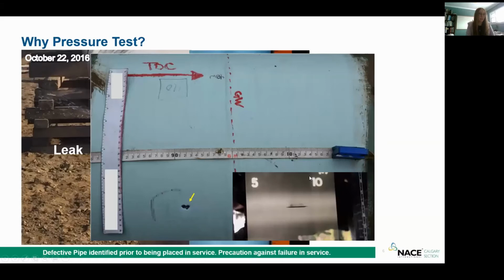Next here is a below ground mainline test, which was unable to hold constant pressure. And this slow drop off in pressure was actually also caused by a long seam imperfection. And this was observed in the leak test because it's below ground. It's tougher to identify those issues, which is why we have that minimum 4 hour leak test. And here is again another X-ray where you can see the lack of fusion that's shown and demonstrated here by the yellow arrow.